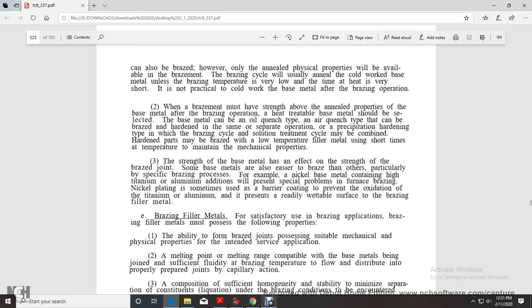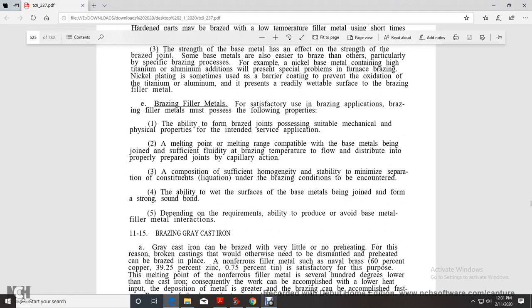For example, nickel base metal containing high titanium and aluminum additions presents special problems, furnishing brazing with nickel plating. Sometimes a barrier coating is used to prevent oxidation of the titanium and aluminum present, so the surface is wettable for the brazing filler metal.